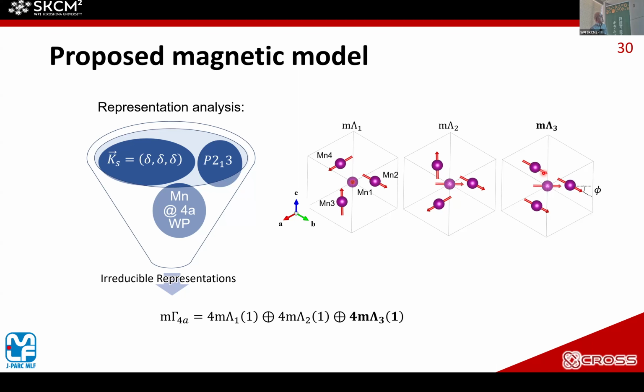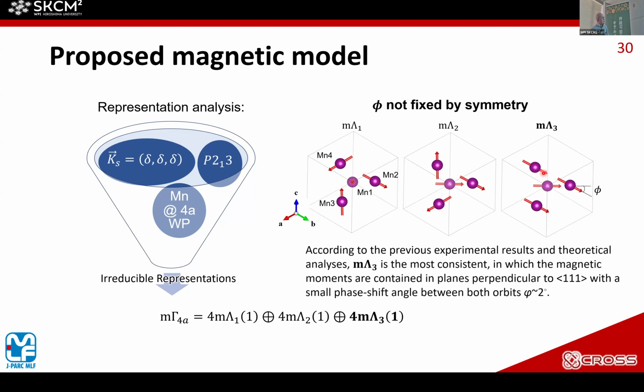So, manganese 1, manganese 2, 3, 4. Each manganese has a spin. In the case of lambda 1, manganese 1 spin is along the 1, 1, 1 direction, and the other spins are in the plane perpendicular to 1, 1, 1. In this case, all spins are in the 1, 1, 1 plane, but the spin directions are like this. And in the lambda 3 case, all spins are in the 1, 1, 1 plane, but the angle of manganese 1 and the others takes a phase shift. According to previous experimental results and theoretical analysis, this magnetic structure is most consistent, in which the magnetic moment is contained in the plane, with a small phase shift of 2 degrees or several degrees between the sites.